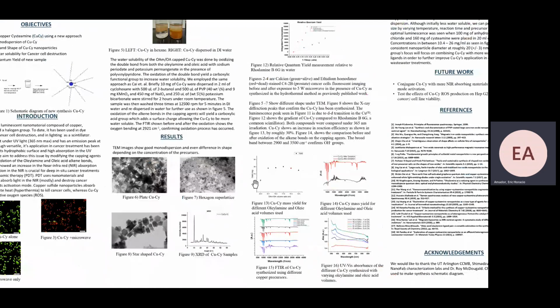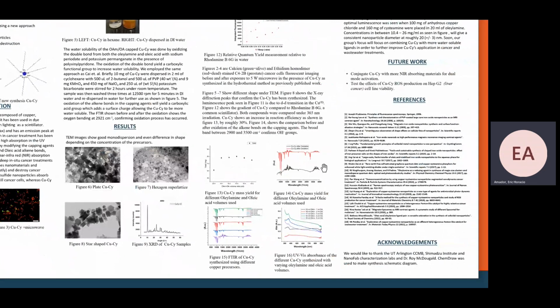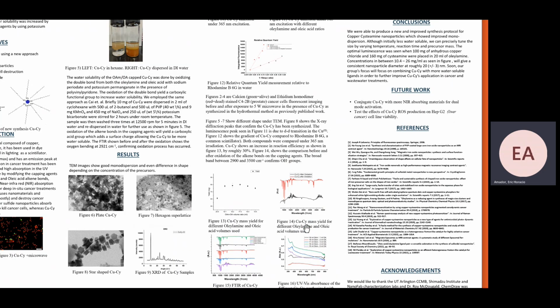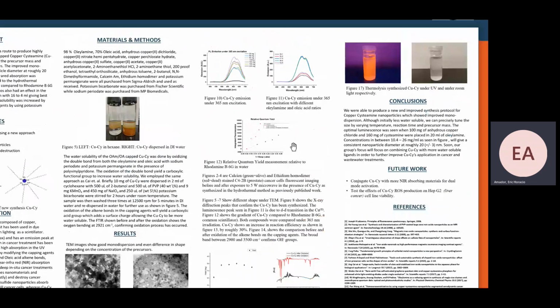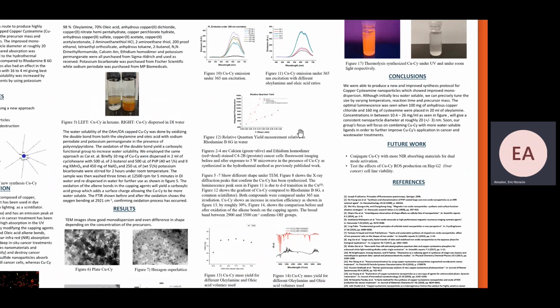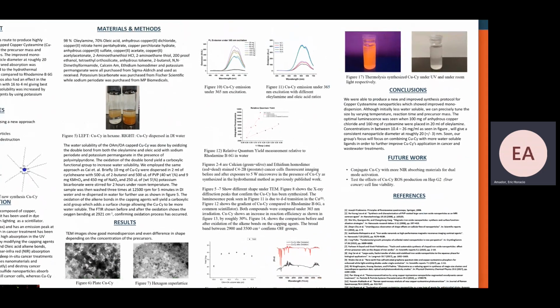Once we did this reaction, we verified using FTIR to see the hydroxyl functional groups on the surface, and we compared it to before and after the oxidation. We also varied the oleylamine to oleic acid ratios and observed that there was a slight increase in the peak of the copper cystamine nanoparticle, which led us to believe that maybe there was an enhancement in the quantum yield, but it does vary it, but it did not improve on the previous synthesis method.